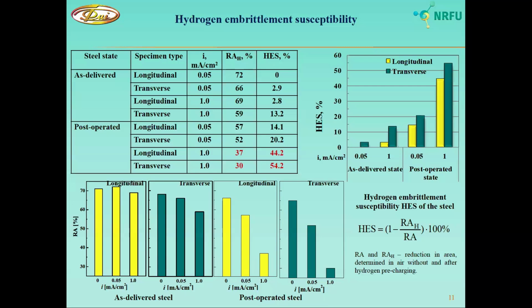And as we can see from this data, as-delivered steel is not sensitive to hydrogen embrittlement under moderate mode of hydrogen charging, and it's somewhat sensitive to it under intensive mode of hydrogen charging for the transverse specimens. And for the operated steel, we can see that it is sensitive to hydrogen embrittlement under both modes of hydrogen charging, especially for the transverse specimens. And also it should be noted that under intensive mode of hydrogen charging, the susceptibility of the operated metal to hydrogen embrittlement is very high.